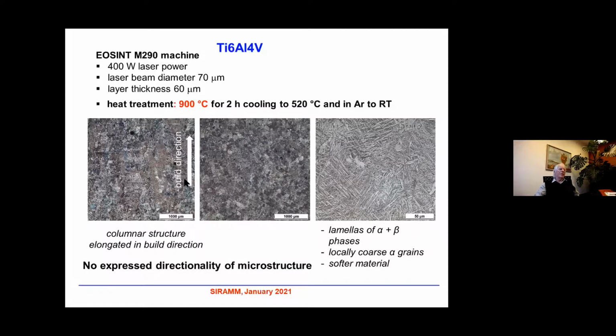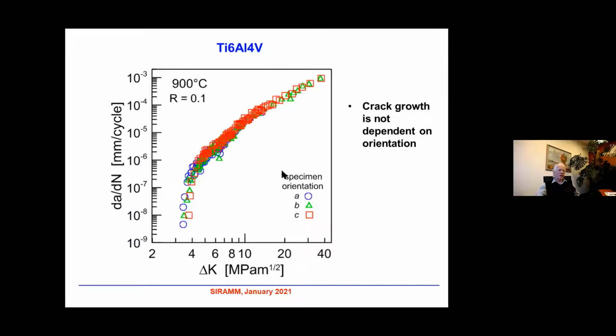This is the build direction. You can see again a columnar microstructure and elongated structure, not so pronounced as in the case at 380. A similar situation on the section by the plane perpendicular to the build direction, and at higher magnification we can observe a little bit coarser microstructure, lamellae of alpha plus beta phases. Locally we can find coarse alpha grains, and the material is generally somewhat softer. So here is no expressed directionality of microstructure.